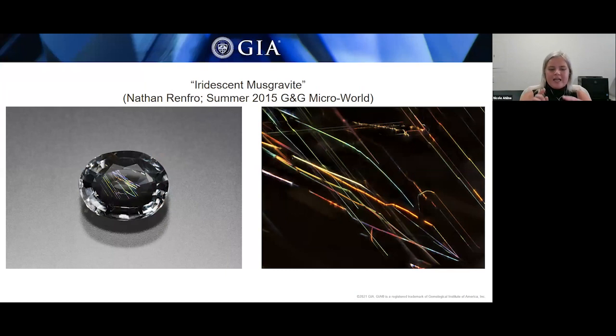So musgravite is a rare mineral closely related to the mineral taaffeite by composition and is slightly sought after by rare stone collectors. This 86-point musgravite, which was identified by Raman spectroscopy, contained numerous etch tubes that broke the surface with fiber optic illumination, and the etch tubes displayed a really nice iridescence. This was the author's first, and I believe only time examining a musgravite that displayed any type of optical phenomenon, at least since this Microworld note was written.